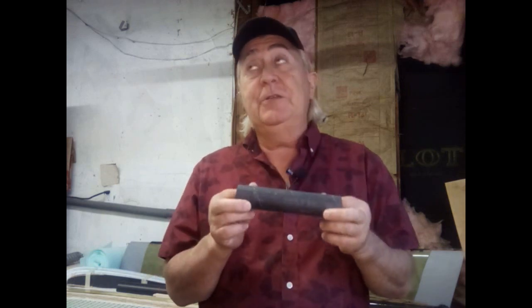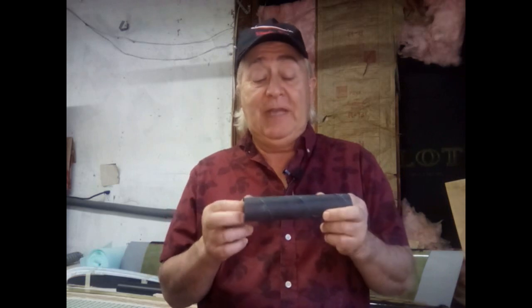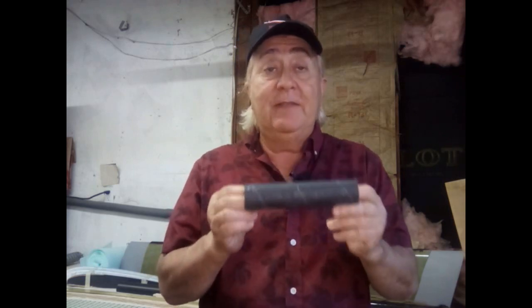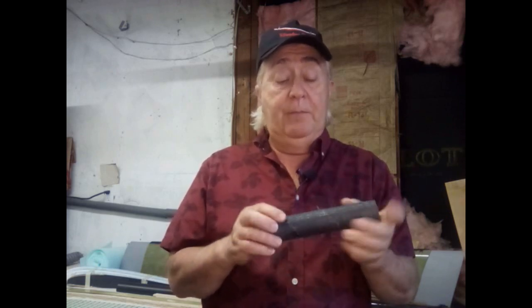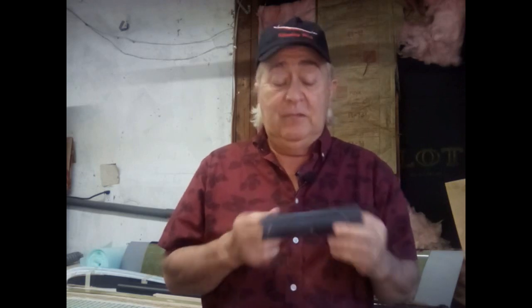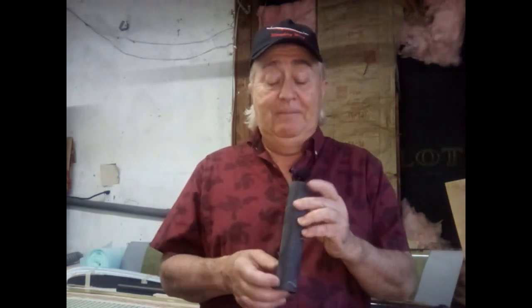So this is probably as strong as aluminum tubing that is 30 to 50 thousandths wall thickness, but it's only 10 thousandths of an inch. Very, very thin, 1 layer. And in bending, it probably would be strong enough if we could keep it from buckling. But what happens is by the time you put enough bulkheads in here, even if they're styrofoam, you go all the trouble to glue bulkheads in here, and you'll prevent the local buckling, but now the weight's back up, and it's not because of the styrofoam, it's because of all the epoxy you used to glue them in there. So you end up chasing your tail on those.